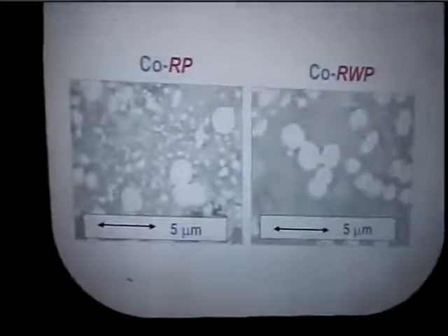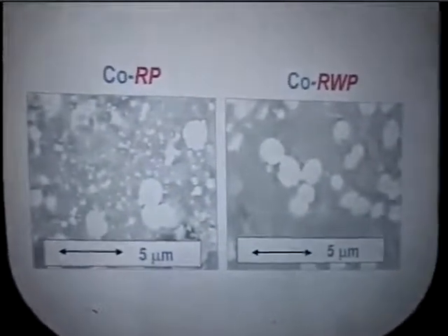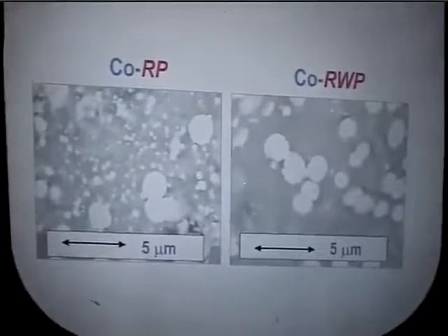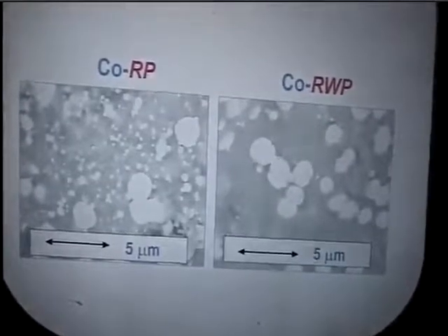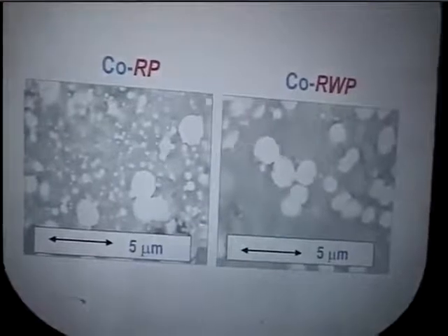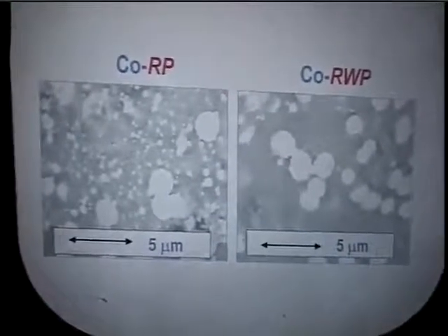At this point, maybe there are two possibilities. Either water vapor can facilitate the agglomeration of smaller cobalt patches to form larger cobalt patches, or water vapor may increase the diffusion of cobalt from the smaller cobalt patches into the alumina matrix and form cobalt aluminate. Maybe both phenomena occur, with the latter being more important, resulting in significant cobalt-support compound formation.